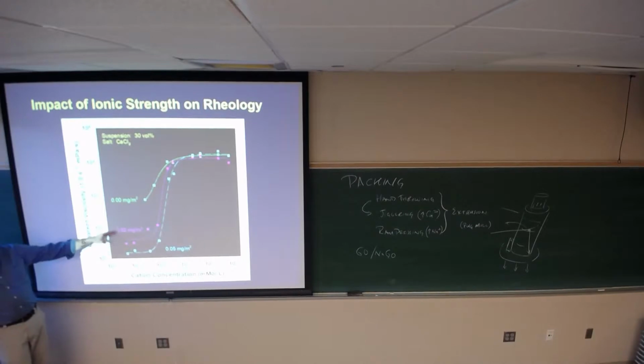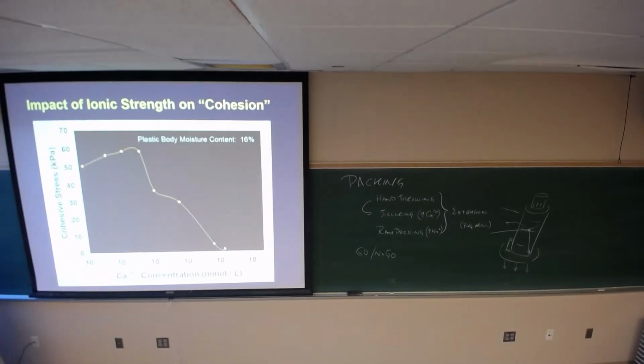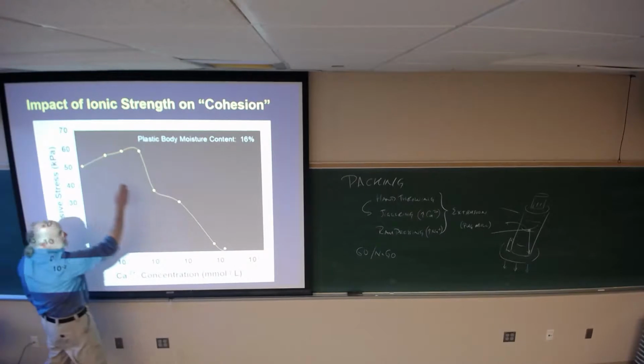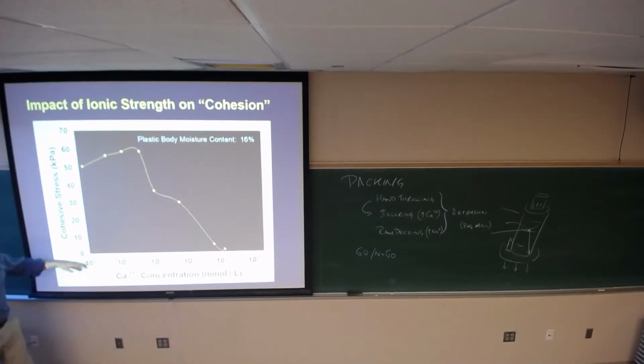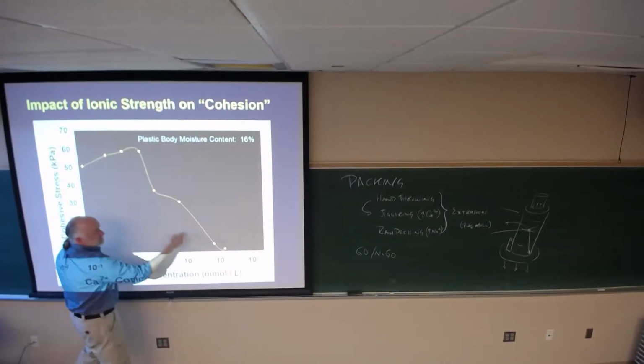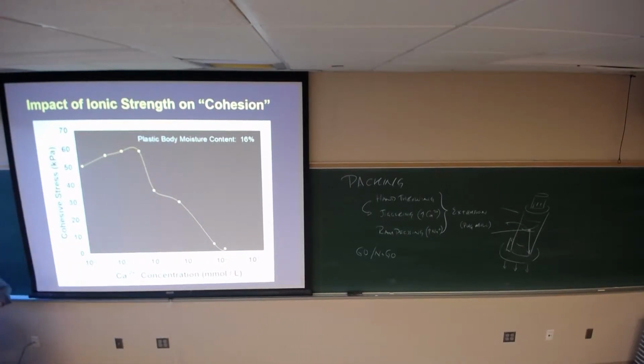You're familiar with this slide, although not with black background, right? So this is the effective ionic strength, calcium ion concentration. And then when we looked at the cohesion of the porcelain body, it's essentially same x-axis scale, log of ionic concentration of calcium, but they are in exactly the same location. This drop in cohesion corresponds with the critical coagulation concentration. Evidence that all those colloidal interactions and particle interactions are still true, even though I don't have any excess water in the system to speak of, right? So ionic strength is playing a huge role in the plasticity of this body.